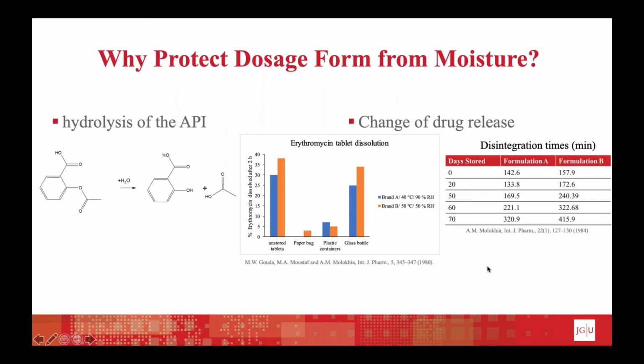The second example is the disintegration time, which can also be changed due to moisture after storing. And here in this example, the two formulations were stored up to 70 days, and as we can see, the disintegration time increased dramatically in these two formulations. So as a result, this could change the bioavailability and so also the plasma concentration time profiles from these formulations.